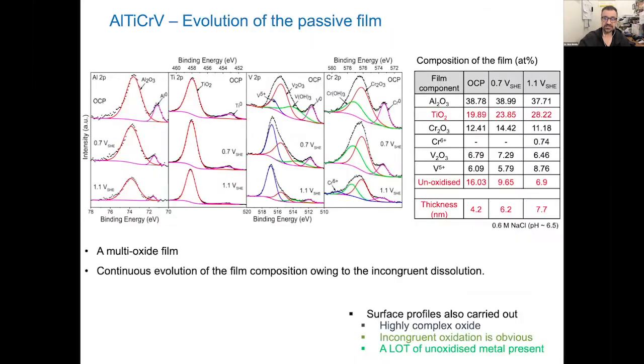So then when you look at XPS, again, I'm going to cut a very long story short here, it turns out that you actually have a multi-oxide film on the surface. And this has been done at different grazing incidents and so forth as well. I'm not going to show all that information, but the composition of the film also changes as you polarize anodically. You get more and more titanium in your film. It's principally an aluminium oxide film. But what's really, really interesting, if you haven't heard me say this before at other talks, I'll say it again, is the very high proportion of unoxidized, so zero oxidation state, metals in the film, which is really, really unique relative to, I guess, single principal element alloys.